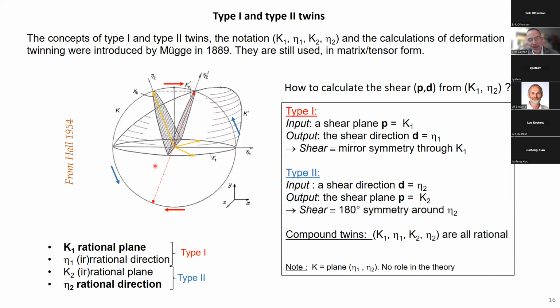We have a crystal, and we want to know what the twin could be. I need to define the twin plane and the twin direction. So in my crystal, I need to define a unit cell. I take 3 crystallographic directions, in yellow here. With 2 of them, I create a crystallographic plane with a low index, for example an HKL value, and I call this plane K1. It's an input in my model. The 3rd direction is a rational crystallographic direction, and I call it eta 2. I do not choose eta 2 randomly. Actually, I calculate the normal to the K1 plane, and I take eta 2 very close to this normal. But the normal is not necessarily rational, whereas this direction is necessarily rational.